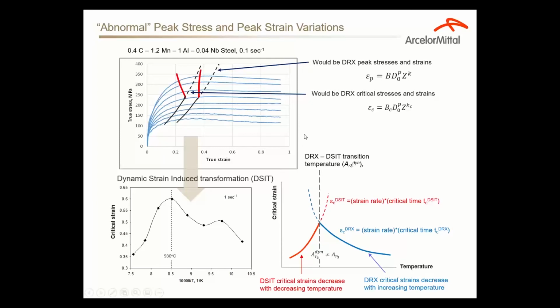One more thing that I would like to talk about here, and it especially concerns plate rolling, is abnormal behavior of some characteristic strains that we see during the compression absorption test. Typically, the peak strain or critical strain for dynamic recrystallization increases as the temperature goes down. However, at some point, we see it starts decreasing as the temperature is decreased. This is a known phenomenon. It's attributed to dynamic strain-induced transformation.